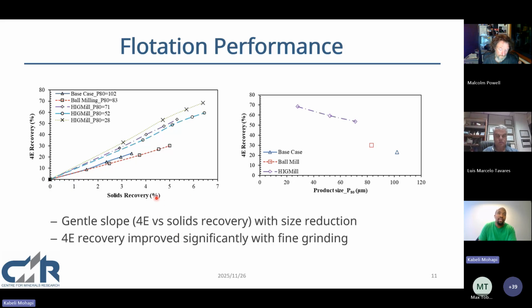In this graph, we plotted the relationship between the 4E recovery of our valuable minerals versus the mass pull. What is evident is that the 4E recovery increases significantly with grinding finer, shown by the fact that the slope of the recovery versus mass pull increases as the particle goes finer.